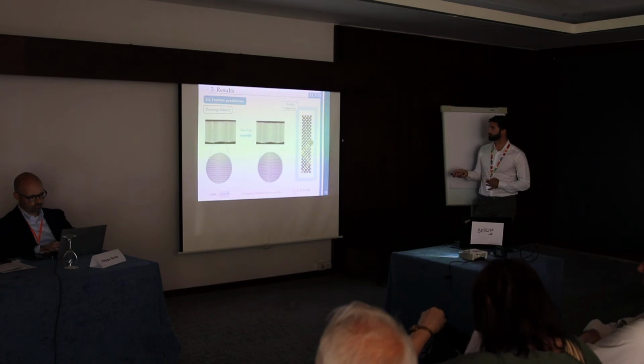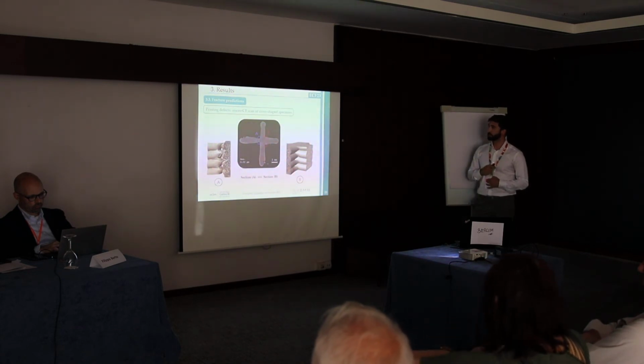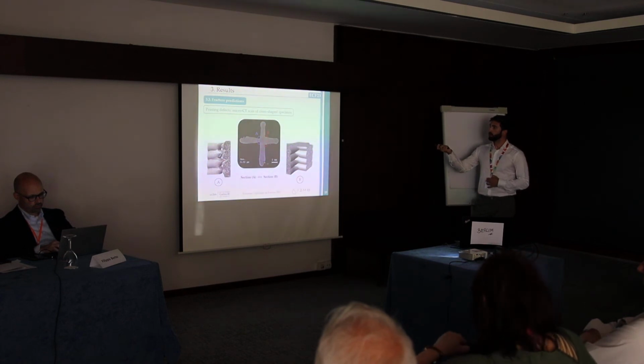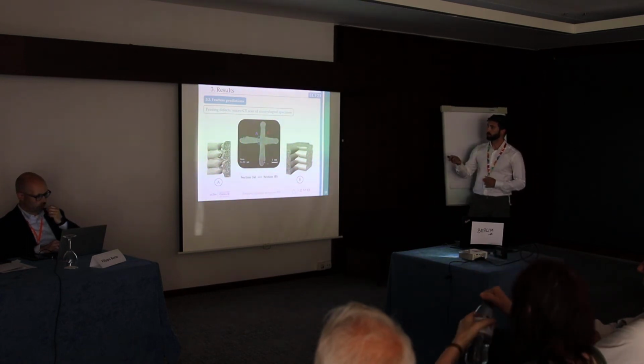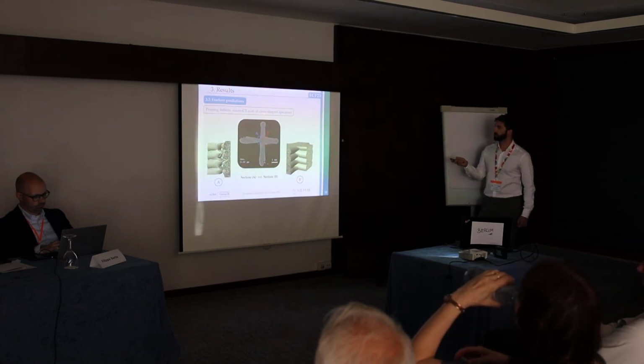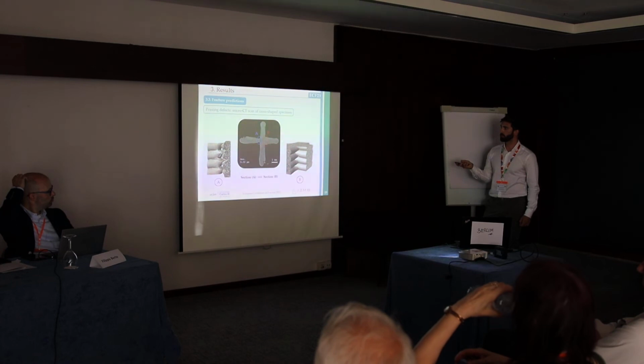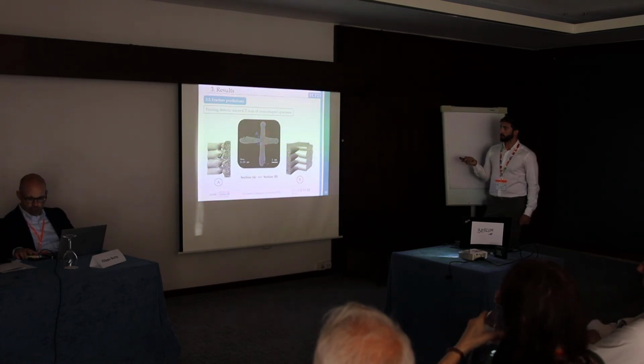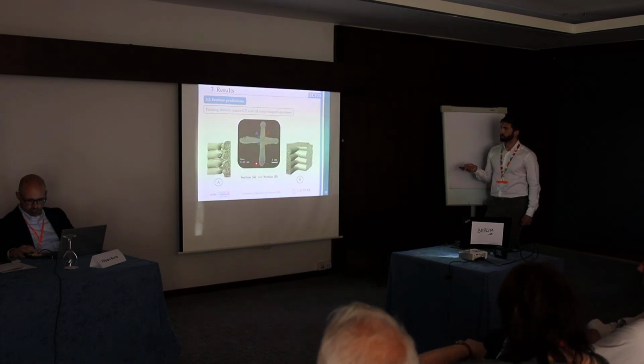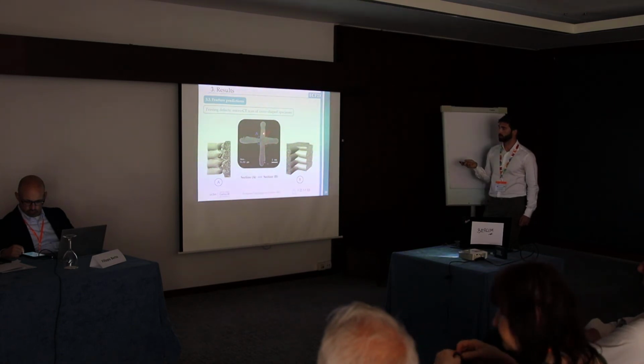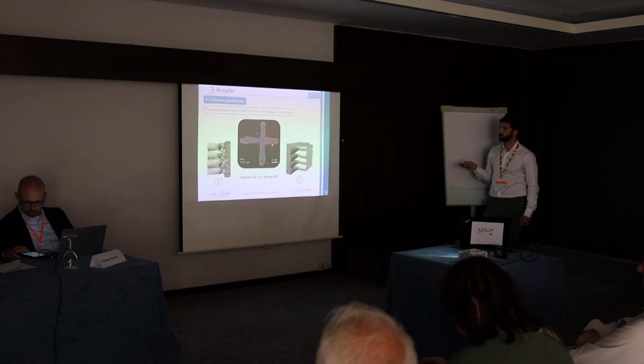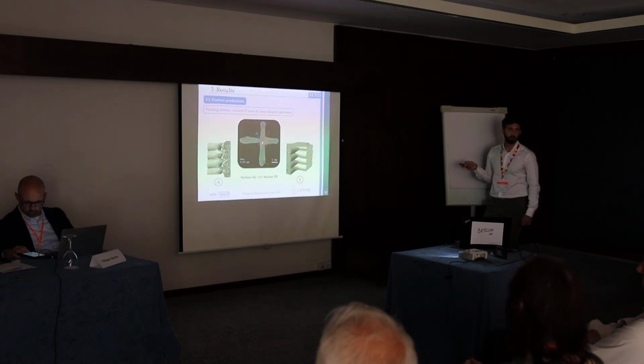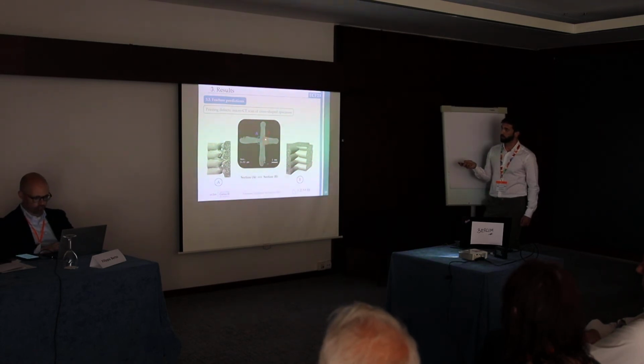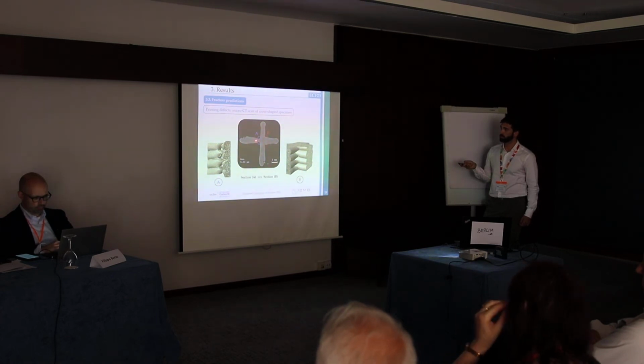and then after the bending, the neck starts growing. Then, to study this failure in detail, we manufactured this cross-shaped specimen. You should know that this vertical line was printed first, and then the horizontal one from right to left. So you can see how, after the first deposited filament, the material is accumulated in this zone. So the cross section here is very wide. The opposite happened on the other side, where the section is very low.